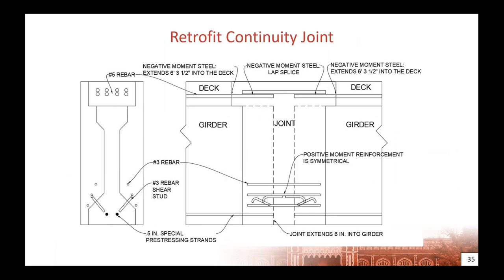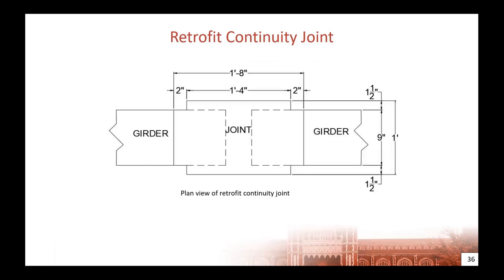For the retrofit joint, we were looking at, again, beams that would already be in place, simply supported, being able to connect the two sets of reinforcement in the deck with a straight lap splice bar in the top, having a narrower joint between the beam ends, so it will be based on the existing girders, and then using straight bars across the bottom to create a connection for any positive moment that was created by temperature effects. We again have a narrower joint between the beams, so part of the beam ends up being encapsulated by that joint. We end up with about a 16-inch total width of the joint, some additional space in the deck, again, to create the splice for our negative moment reinforcement.